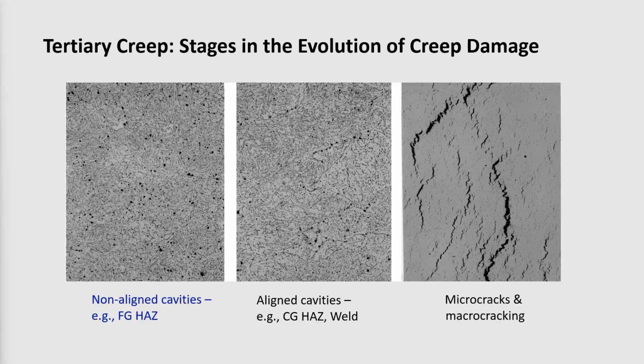This is a good indication of the evolution of the damage. You can see on the micrograph on the left, this is basically non-aligned cavities. The middle micrograph is aligned cavities. And then on the right would be microcracks and macrocracking, which would represent an advanced stage of the damage. What I'd like to draw attention to, though, is that those of you who have dealt with suppliers who come in and evaluate damage, oftentimes you'll see descriptions of the damage that go through a progression from isolated cavities to oriented cavities to microcracks and to macrocracking. That description of the damage is applicable for certain structures, particularly for coarser grain structures. It's not necessarily applicable to fine grain structures.